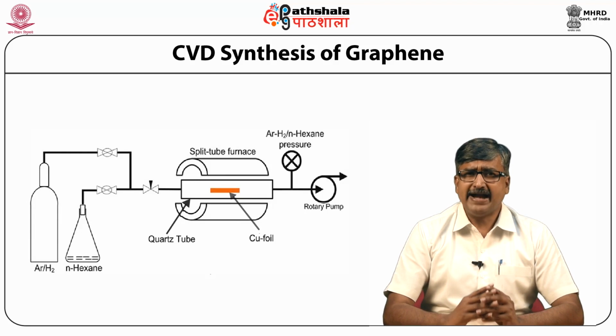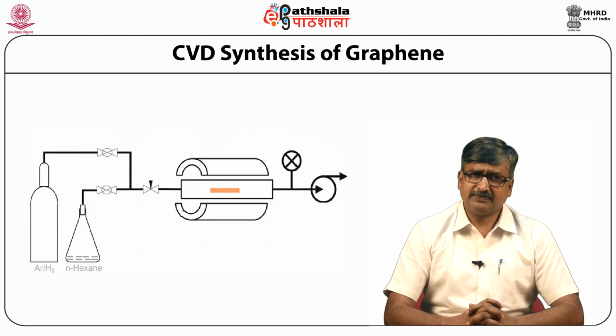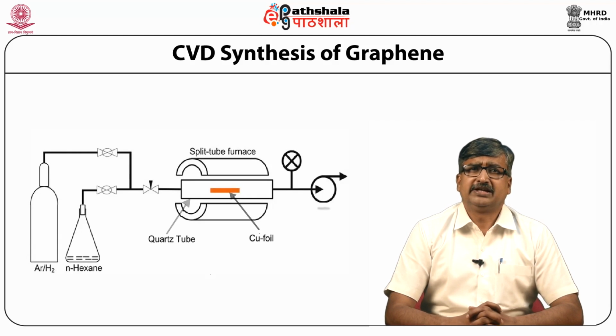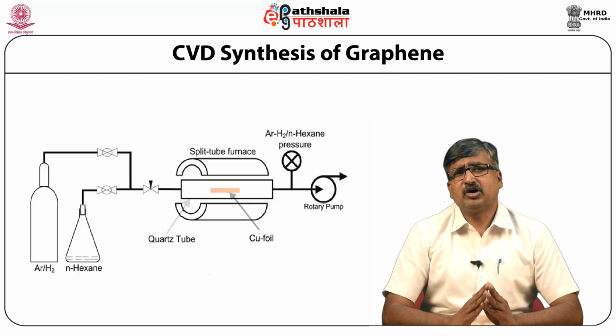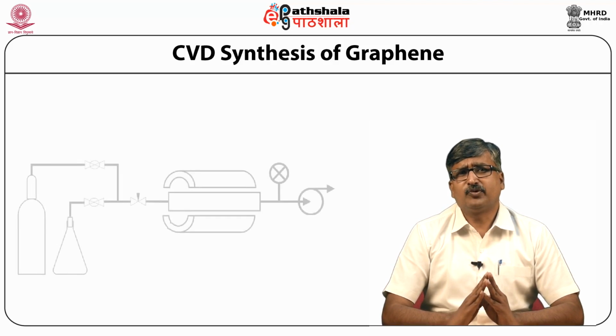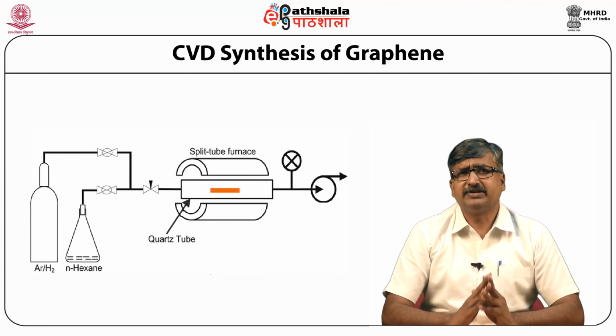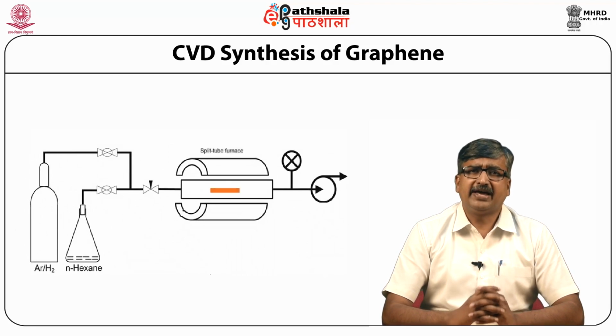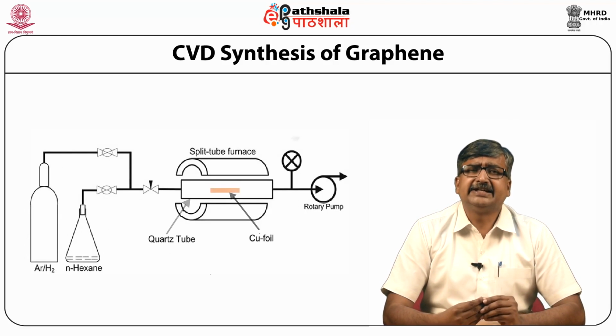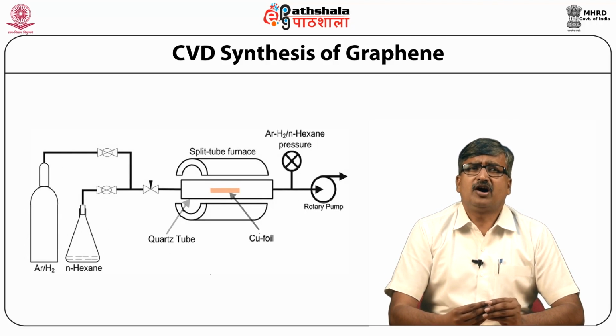Another important issue is opening of a band gap in graphene by chemical doping in the carbon lattice. Liquid precursor based growth can help in realizing graphene doping because nitrogen and boron containing organic solvents like pyridine or triethyl borane are inexpensive and easy to use, whereas organic gases containing dopant atoms are rather uncommon.